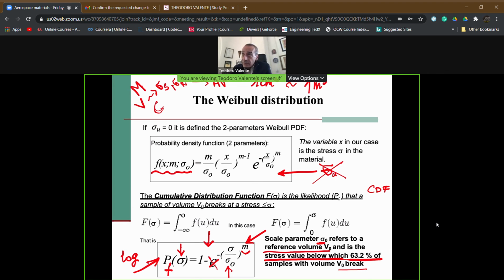Because the poor behavior of the ceramic materials in tension is related to the pre-existing defects. Thus, if we have bigger volumes, this means that the probability of having bigger defects inside or on the surface of the material is higher. So we can find bigger defects. And given that the fracture toughness is not modified by the volume, the material can tolerate lower stresses. Or, which is the same thing, if you apply the same stress as on a specimen with a lower volume, the probability of failure is higher. And this must be remembered.